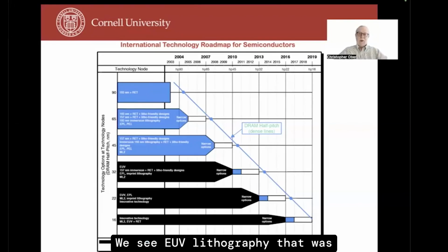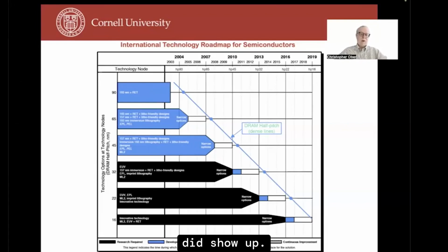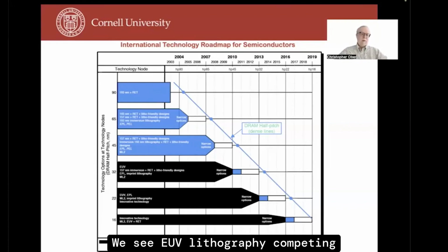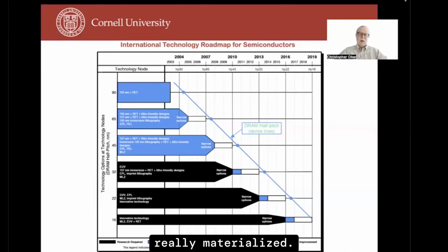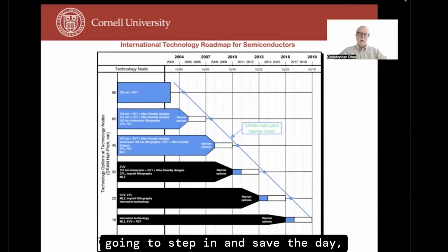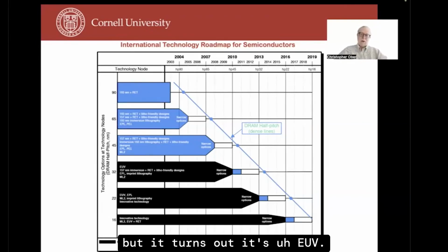We see EUV lithography that was supposed to kick in around, well, between 2010 and 2013. And it was delayed a little bit, but it did show up. We see EUV lithography competing with electron projection lithography, and EPL has never really materialized. And now we are looking at what they said was innovative technology, which was going to step in and save the day, but it turns out it's EUV.